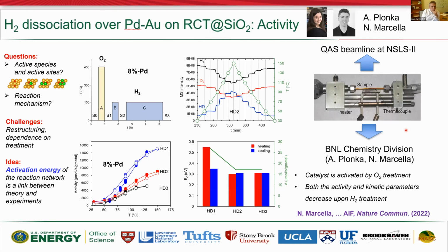So in our seed project, the project that I told you we started about 1.5 years ago in IMASC, my postdoc Anna Plonka and the student Nick used this reactor, a very typical workhorse reactor, we would call it, also called a Clausen cell, where we do operando experiments using X-ray spectroscopy, also X-ray diffraction, and measure activity at the same time, simultaneously. So this reactor was used to measure activity for hydrogen dissociation. It was actually not hydrogen dissociation, it was HD exchange, because it's very difficult to detect hydrogen dissociation products by mass spec.